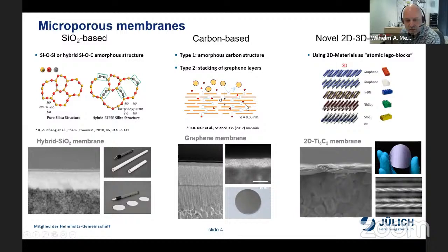If you look at the microstructure in this image, you see a membrane layer which has a thickness of only 100 or 200 nanometers. All the other things you see here are intermediate layers or porous support layers. That means we have a graded structure. We start with a pore size in the support of maybe 100 nanometers, then we decrease the pore size in the intermediate layers, and the functional layer, which you can see here, has a pore size of only 0.2 or 0.3 nanometer. There are also other membrane possibilities, for example the so-called MXene membranes, which are titanium carbide membranes,